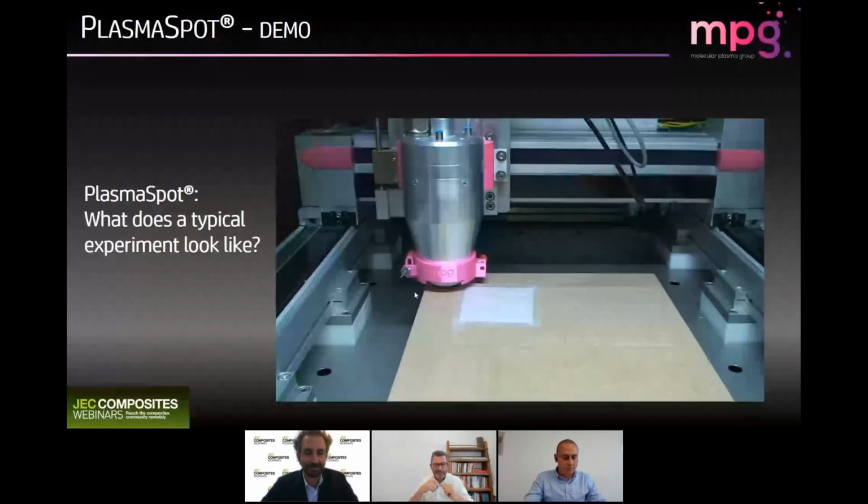What I do want to say is that we typically deposit very thin coatings in the order of 10 to 100 nanometers, and they're organic in nature. So you do need to be aware that the abrasion resistance is relatively limited, because nanometers of organic is not going to be a hard, very abrasion resistant coating. Which is also why, in the case studies I mentioned earlier, it's always working on that interface towards something. We do have some applications where we deposit the top coating, but they're rare. They need to be in environments where there's no abrasion. Okay, thank you, Mark.